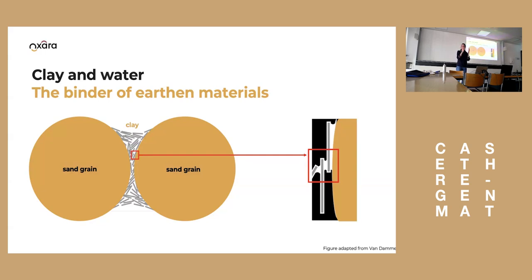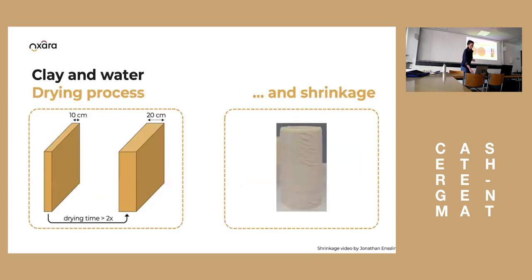water-clay interaction, and also this principle that is defining for 4 aspects that I want to point out on the earthen building materials. So first of all, on this clay-water interaction that is important, it's the drying. So when you want to build with earth, in very general, you need to add water to the clay to make it workable to whatever consistency. And once you place your material, it needs to dry. And that drying is really a drying. So all the water needs to evaporate, unlike in cementitious systems, for instance, where the water gets bound by a chemical reaction. Here, everything that needs to go out needs to evaporate.